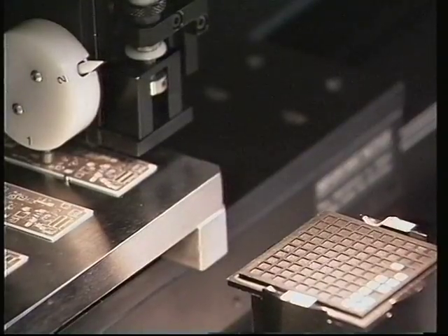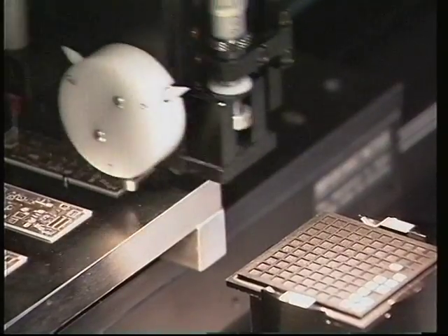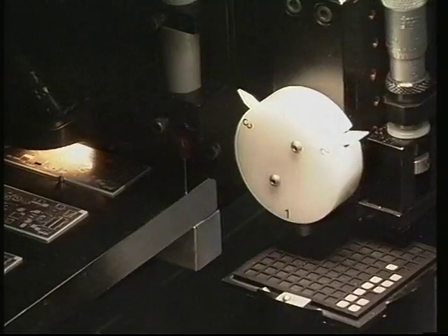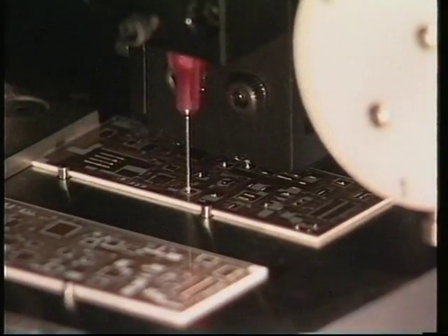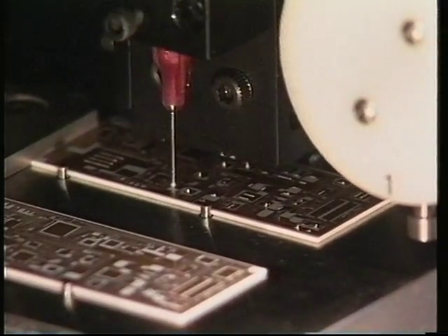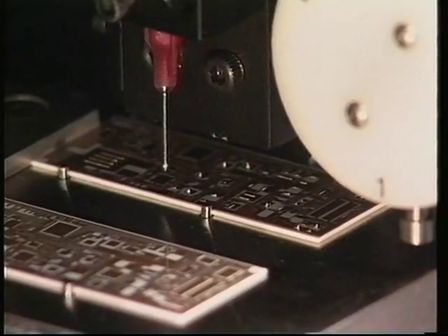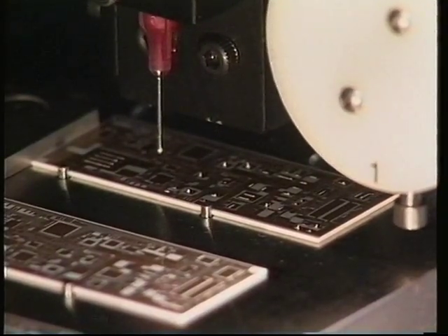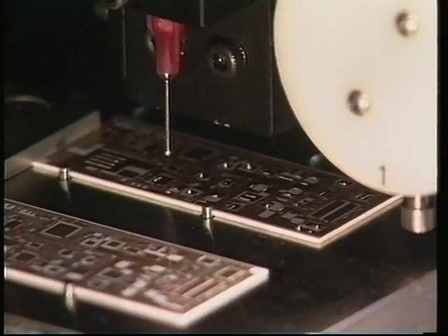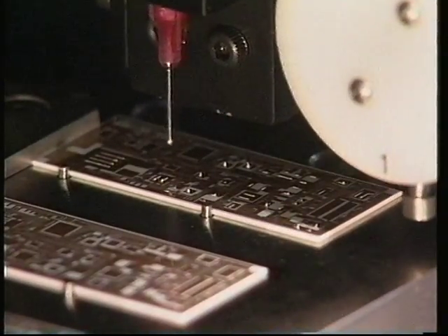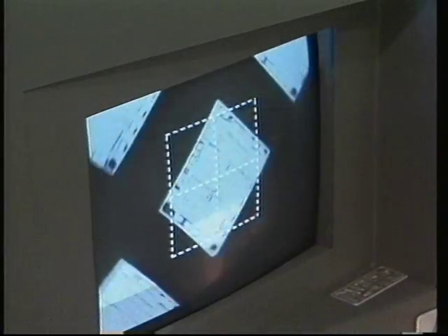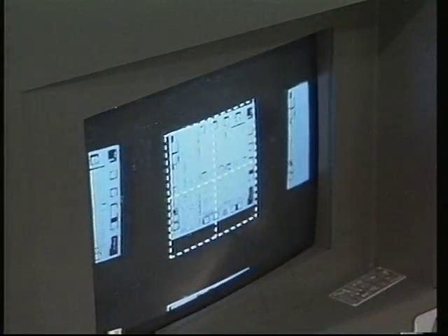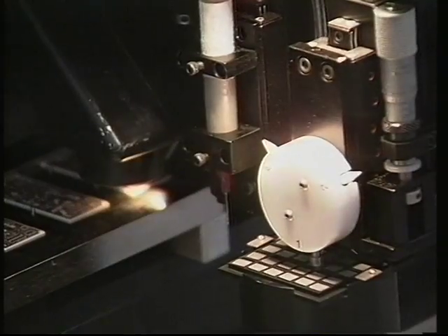The silicon chips are glued onto the substrate in the so-called die bonding process. A drop of epoxy adhesive is applied for each chip. Capacitors are also glued. In this case, the adhesive provides electrical contact as well as mechanical support. The adhesive is cured at 165 degrees centigrade for about 2 hours.